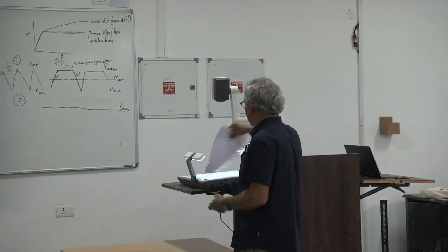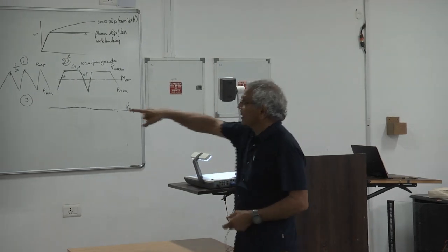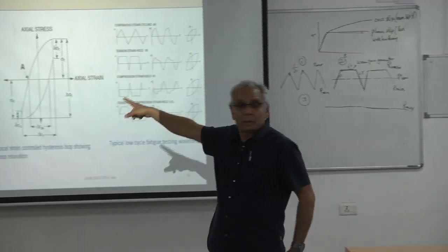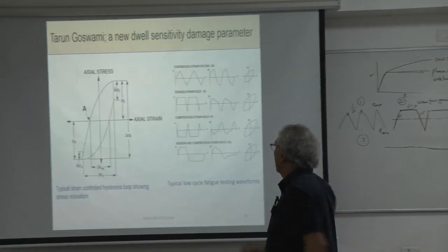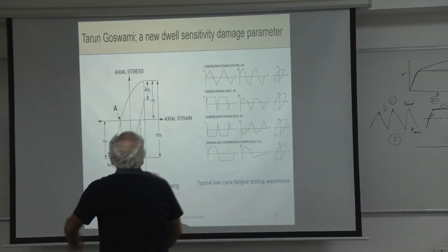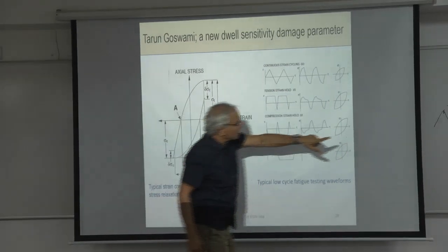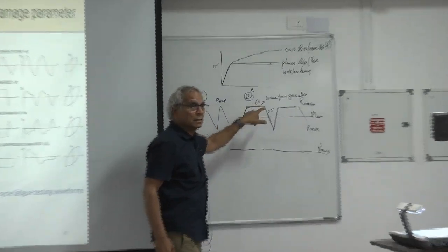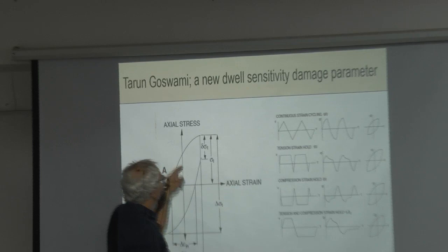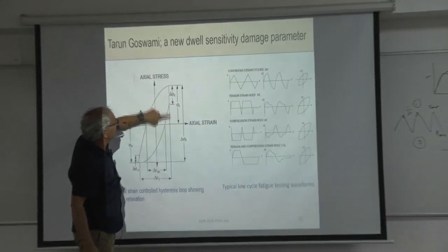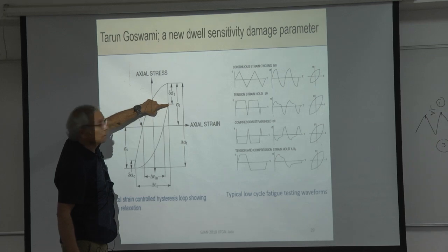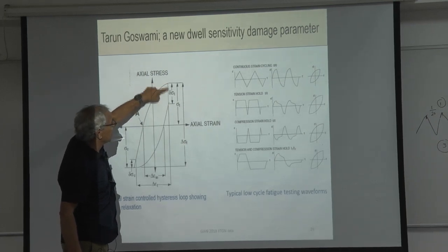I got all these things in for you. Goswami, not Majumdar, did some low cycle fatigue, these kinds of dwell fatigue tests. Basically, instead of holding at constant load, this is a constant load, constant stress, constant K test. Here, it's a low cycle fatigue test, and you're holding it at constant strain.